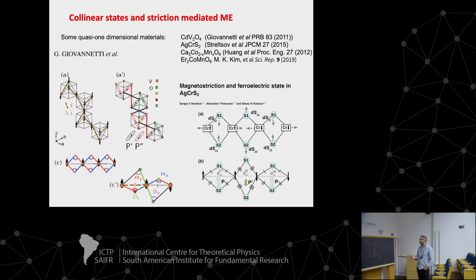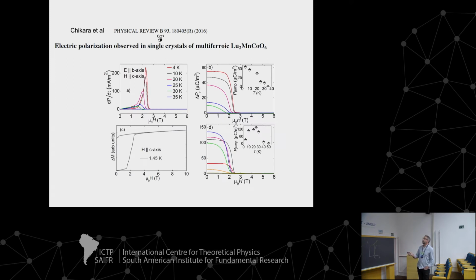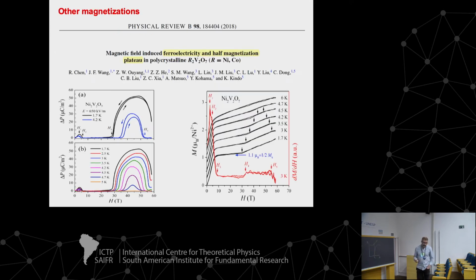Okay, so these are other materials, never mind. This is another one of these double perovskites that also shows vanishing of P at the same point where M increases. There are also other cases that are related in some way. For example, this nickel vanadate has a magnetic one-third plateau. If you look at magnetization as a function of the magnetic field, you see there is a one-third plateau here. And when you look at the variation of the electric polarization, when you go in and out of the plateau, you see changes, while there are no changes within the plateau.